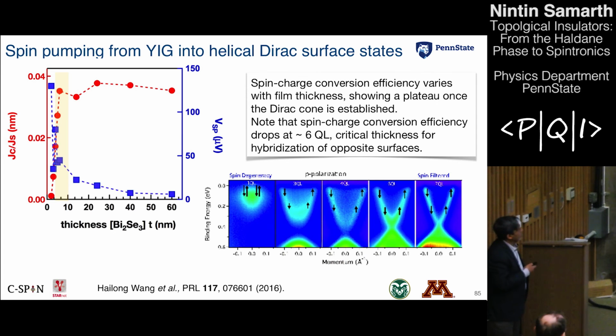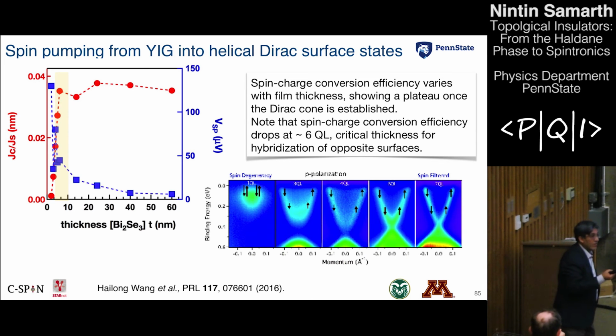And we believe that because of this correlation between what's happening as a function of layer thickness and what we know from ARPES is happening to the band structure as a function of layer thickness, what we are seeing here is clear evidence for spin pumping from the ferromagnetic insulator into the states of the topological insulator. And in this case, we have absolutely no artifacts that are due to conduction through a parallel layer or anything of that sort, right? So we believe that this is the way in which we can actually try to systematize what's going on in